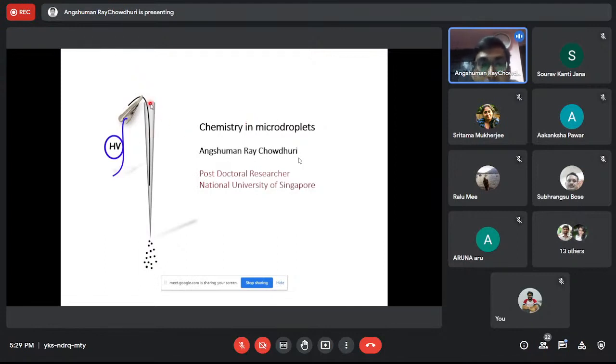For that, we will take some metal ions, that means the precursor, in a capillary tube. It will be a glass capillary, and we will put a metal wire, just like a platinum wire, into it, and we will give some potential to the platinum wire electrode. Eventually the solution will come through that capillary as droplets. We will call this a spray, and some spray plume will be generated.